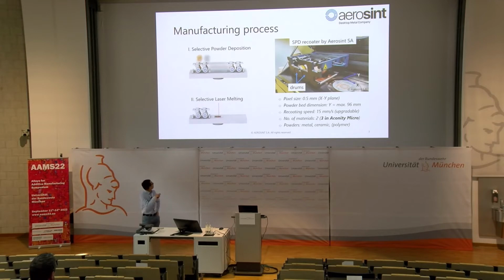And then at the bottom of the cylinder, we have an array of valves, which you can locally control the opening and closing to eject a pixelized powder. That's why our pixel size is around 500 micron at the moment. We are also working on upgrading to 300 micron.